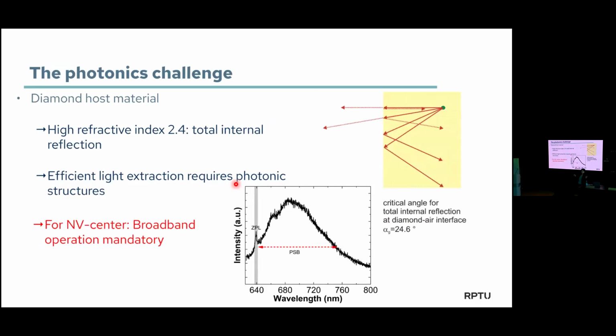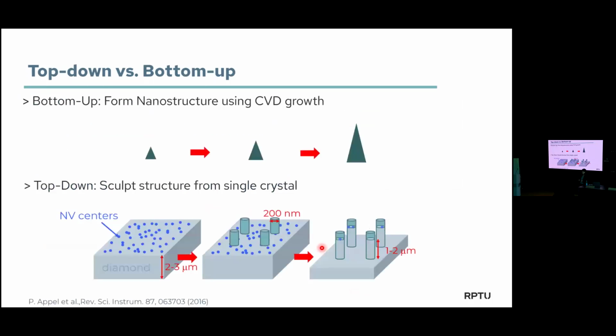This is the one thing. The second thing is we love the NV center for its spin properties, but we hate it for its emission properties because it has a very, very broad emission due to phonon sidebands. So always when we think about doing photonics, we need something that works broadband. Even if we could do nice high finesse cavities, it's not necessarily what we want here. We more want waveguides that can work with this broad spectrum. And still, we have to keep in mind, it should not only be a photonic structure, it should also be a tip that we can scan.